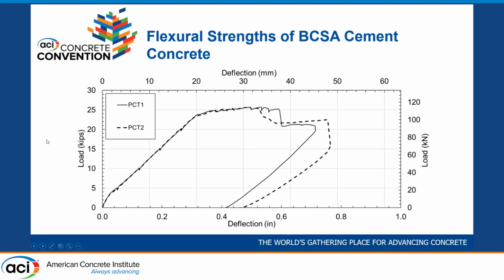So if we plot the BCSA beams on here that were tested at 2 to 5 hours, as soon as we could get them out of the forms and into the load frame, you can see they plot right on top of the Portland cement beams. And the Portland cement beams came out of the exact same batch of concrete. These BCSA beams were actually 2 separate batches, but you can see we got really consistent performance. The cracking looks like it occurs at about the same time. Yielding occurred at about the same time. We actually appear to have a little bit more ductility before the BCSA beams crushed.